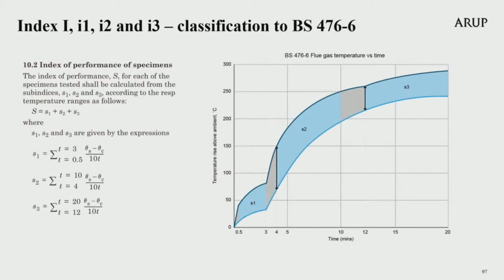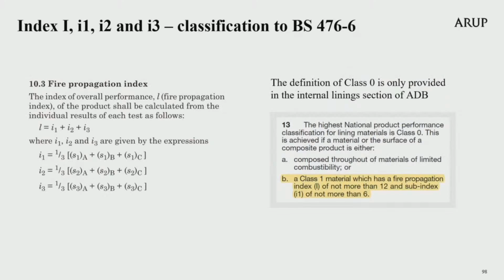From the graph of temperature versus time, 3 distinct time periods are then considered. From 0.5 to 3 minutes, where the difference in temperature is calculated at 0.5 minute intervals. From 4 minutes to 10 minutes, where the difference in temperature is calculated at 1 minute intervals. And from 12 minutes to 20 minutes, where the difference in temperature is calculated at 2 minute intervals. These values are then used in the formulae shown on the screen now to obtain S1, S2 and S3. The calculated S1, S2 and S3 values are then averaged to obtain little i1, i2 and i3, where I is then the sum of these sub-indices.